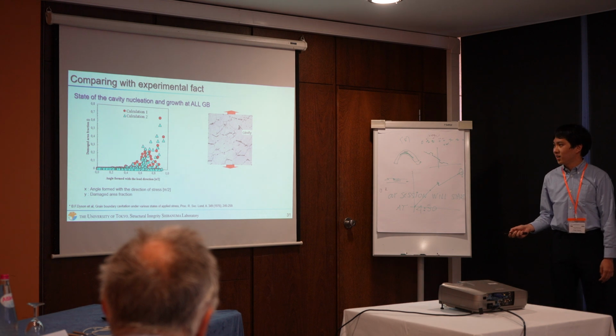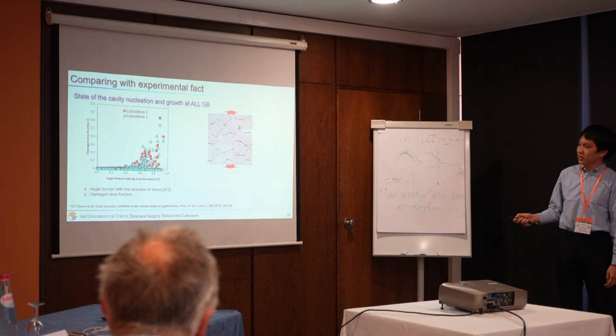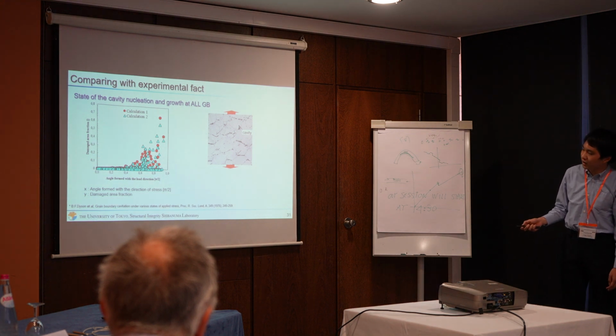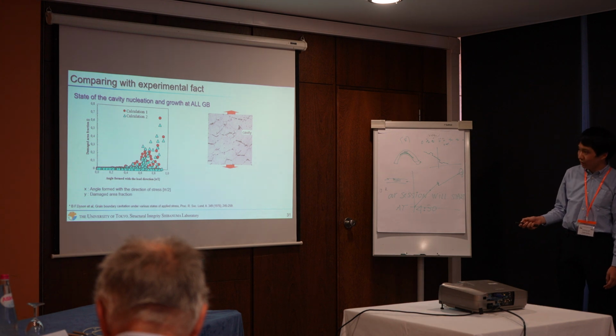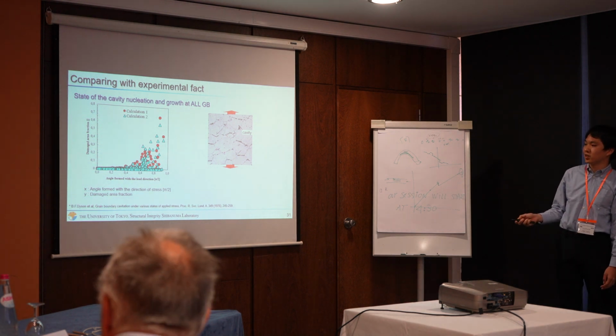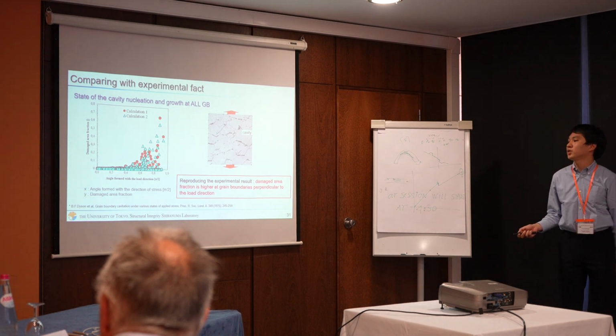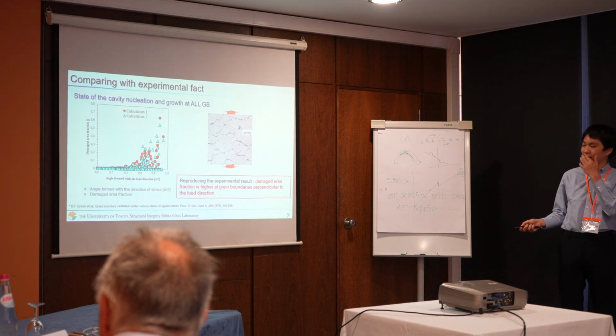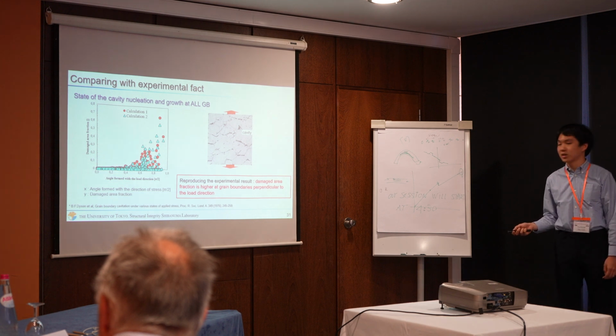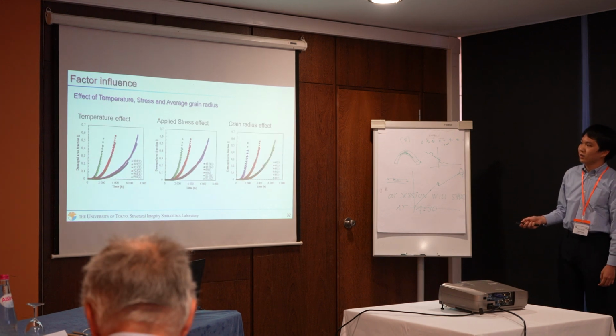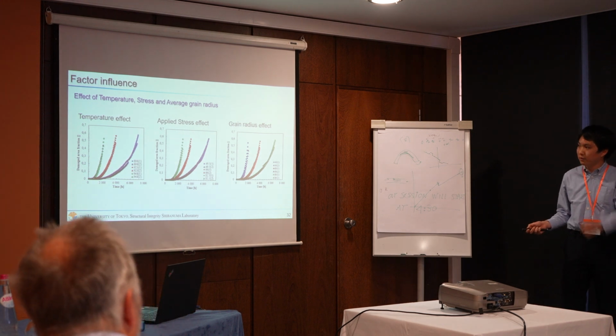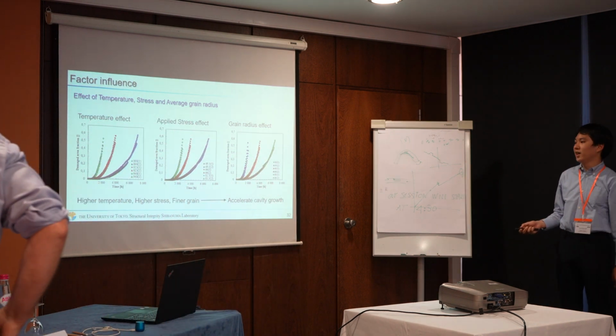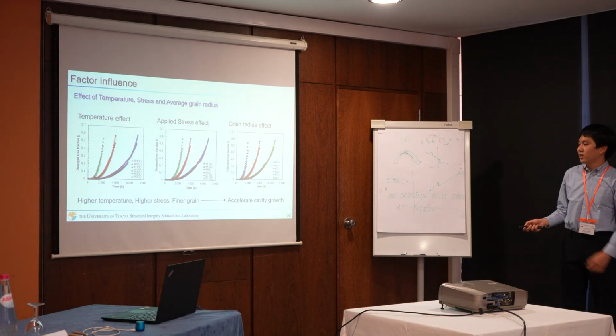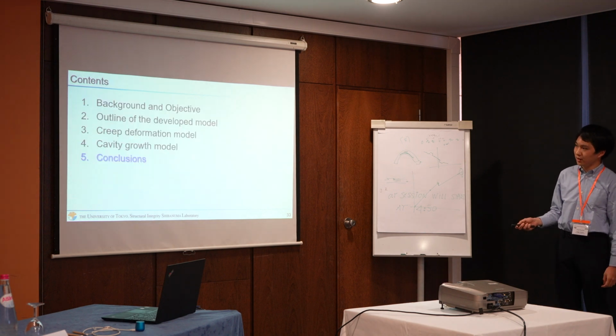And this is a picture of the experiment. The stress is applied in this direction, and more cavities occurred. More cavities occurred at the grain boundary perpendicular to the stress direction. So this model reproduced the experimental result that the damage area fraction is higher at the grain boundaries perpendicular to the load direction. And also, we evaluated effects of temperature, stress, and average grain size. So with higher temperature and higher stress and finer grain, the cavity growth and nucleation is accelerated.